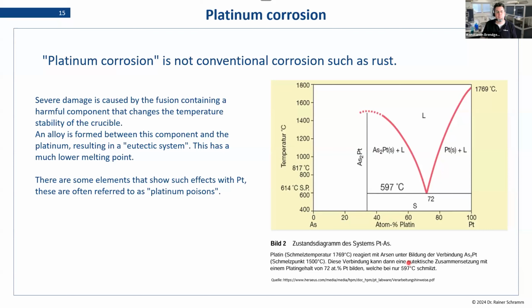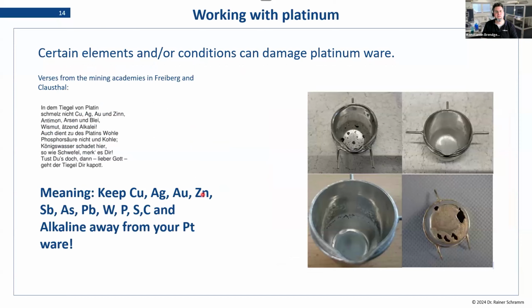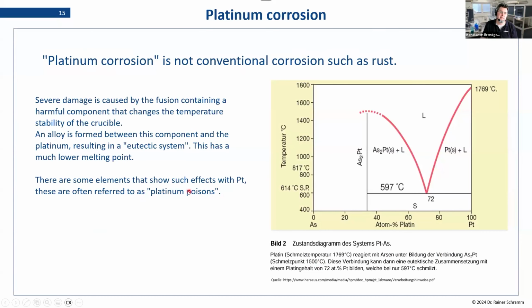So the problem with certain elements is that they can form alloys with the platinum, and they drastically reduce the melting point of our alloy, making it possible to actually disintegrate. And these elements that were mentioned before that can have these effects are usually called platinum poisons. And so we'll have a table in one of the next sheets to show what elements are dangerous to platinum. If you want to have a look at the description, this whole thing is called a eutectic system. Eutecticum in German. Wikipedia has a nice entry on that if you're interested in the real effects.